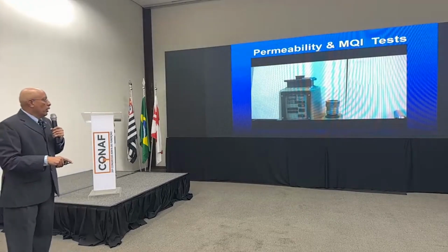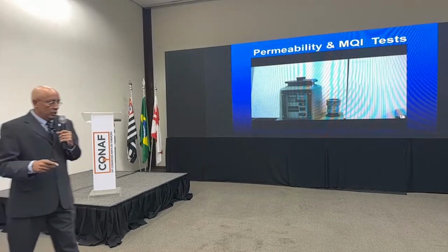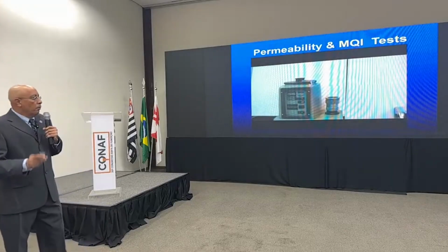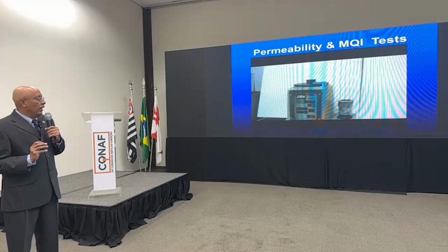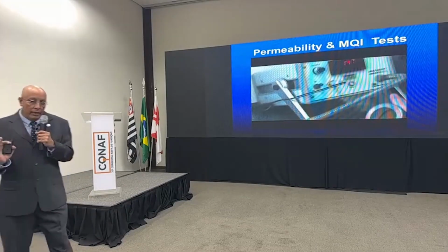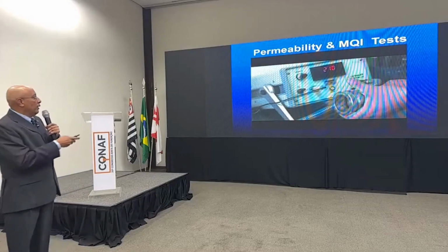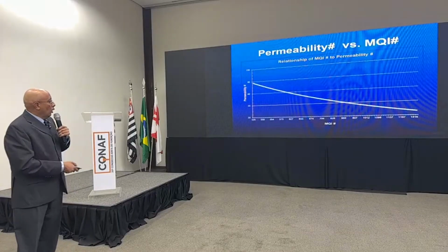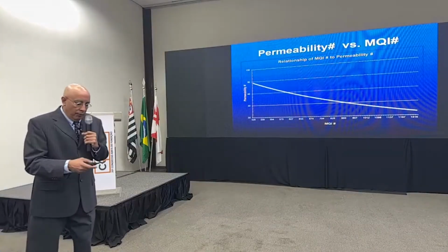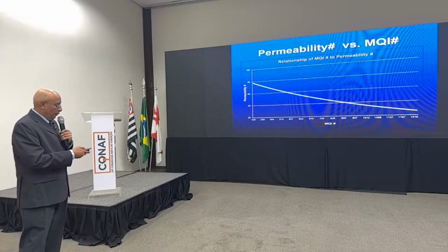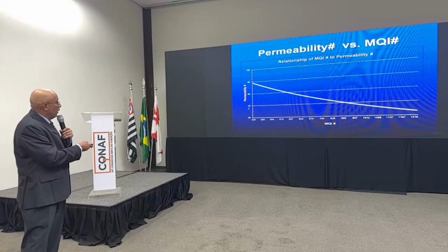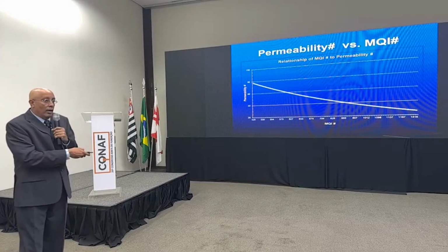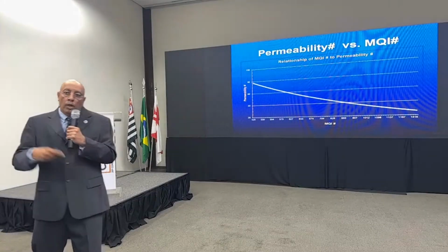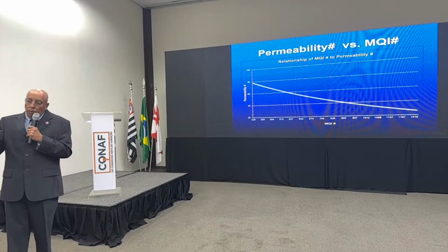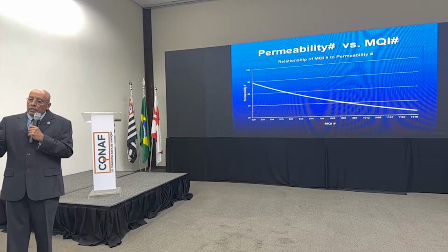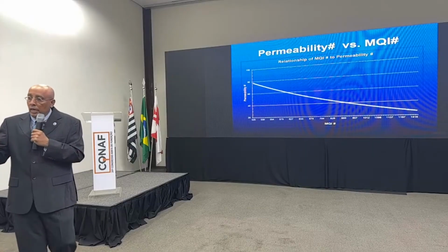But then we will use the MQI test, which is a mold quality index standard, based on a pressure of air and the resistance to the pressure of that air from traveling through the specimen, that we get a direct number. What we have done, we have collected this data to find that there is an inverse relationship between permeability and the MQI values. And this now will allow us to measure more important characteristics of the sand that we could use as property data, such as Darcy's numbers.